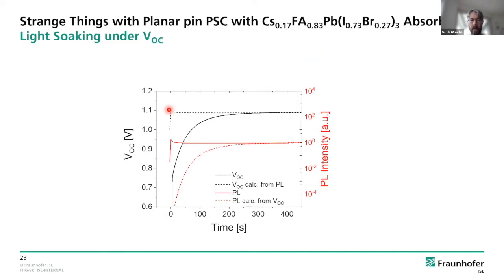Okay, now let's look again at this result. We want to understand why this is happening. We had an idea of what for sure has to be going on in this device, that you can have such an extreme decoupling of the PL intensity and the open circuit voltage. Again, I remind you, the red solid curve is the measured PL intensity. And if we derive straightforwardly from the theory the open circuit voltage that we would expect from this, we end up with a dashed black line. You can see in the end, of course, they are the same, but during the first 200–300 seconds, the open circuit voltage is so much lower.